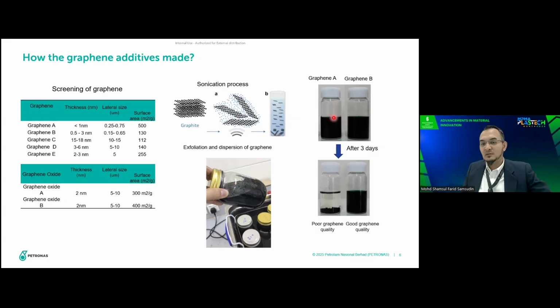After we exfoliate using this sonication process, we leave it for 3 days, and then we monitor again how good the dispersion of graphene in the solvent is. From there, we can see that for the poor type of graphene, sedimentation happens. And for the good graphene, because of the good exfoliation of the graphene particles and layers, it can stabilize for a longer period of time.